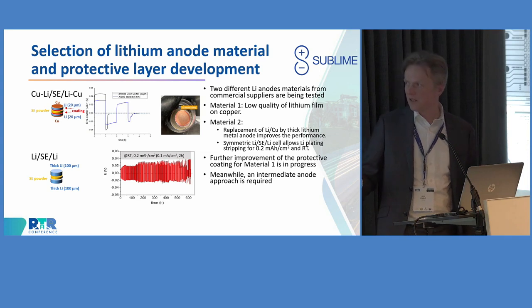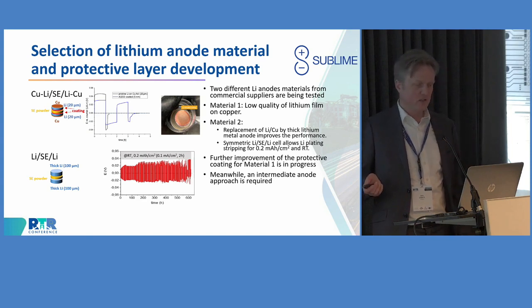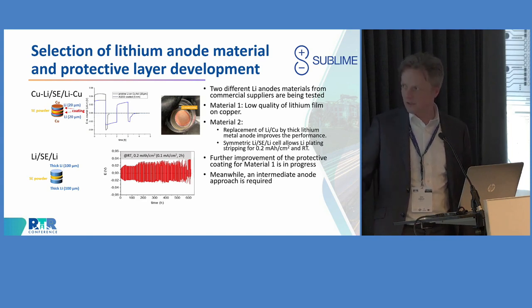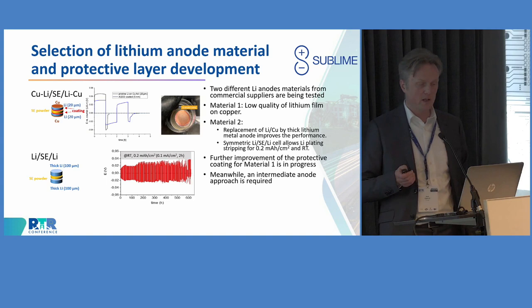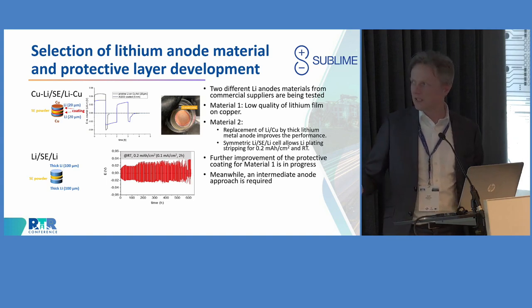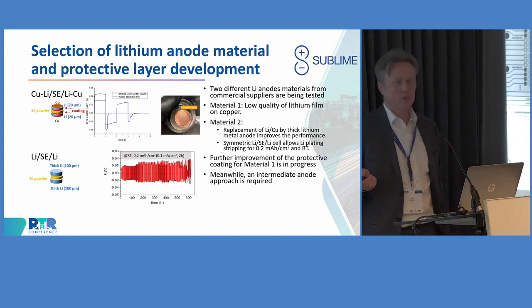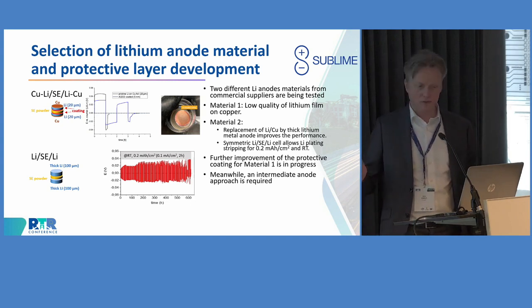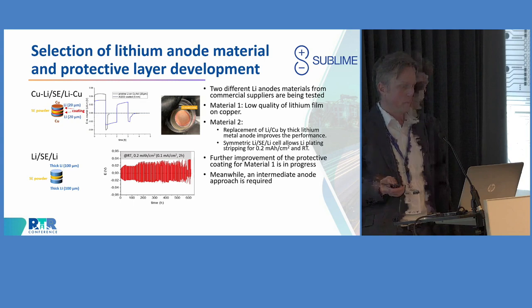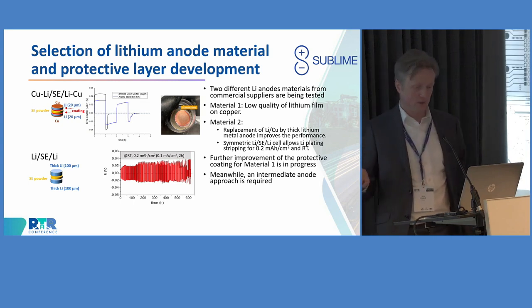However, these are thicker lithium cells, thicker lithium anodes, of which then at the end we don't need that much. There is even more material than we need for active material, and that's the reason why we have to develop here a little bit more on this technology brick. But we see in principle that our Sublime approach works, but of course there is some more optimization needed.